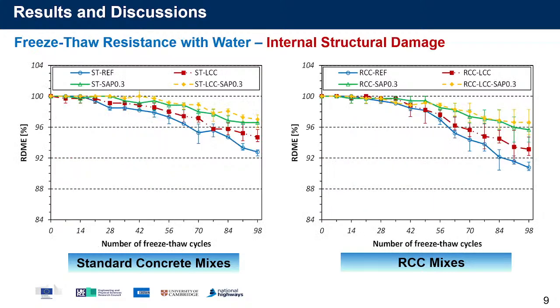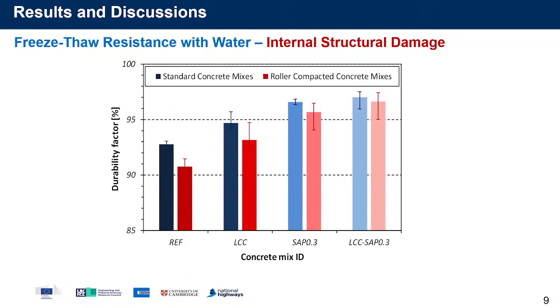In terms of freeze-thaw resistance without de-icing salt, you can see that by increasing the number of freeze-thaw cycles, we have a reduction in the internal stiffness of the concrete because of the introduction of microcracks inside the concrete. Again, the worst performance was achieved in the reference concrete, while with the addition of SAPs or replacement of Portland cement with GGBS, we have seen an improvement in the performance of the concrete. This slide also shows the durability factor of concrete samples. As you can see, based on the standard, all the concrete samples developed in this study meet the requirement of achieving more than 90% durability factor.